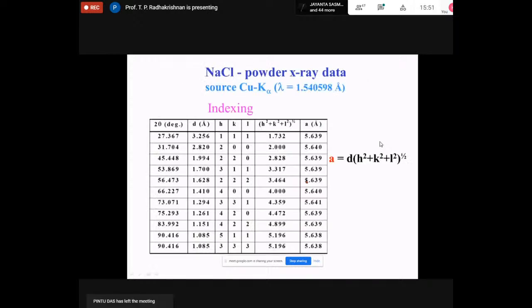So in this indexing process, you actually try out different crystal systems and the corresponding equations and try to see whether this data which you have, which is raw experimental data, can be indexed to a certain set of Miller planes, yielding a unique set of unit cell parameters A, B, C, or alpha, beta, gamma. Those are the six parameters which you'll have in a triclinic system, the lowest symmetry system, or a single parameter A in cubic, which is the highest symmetry system.